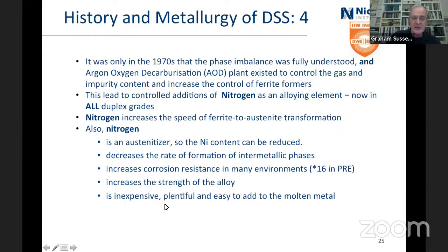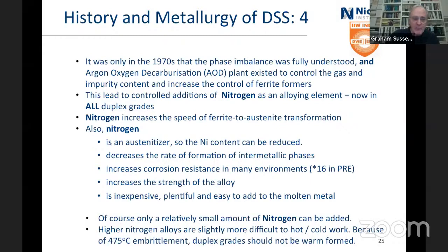It's nice and inexpensive, it's plentiful, it's easy to use. The only problem is you can't go beyond about 0.6%, but still, that's good and helpful. Of course, only a very small amount is needed, as I've said, just 0.6. The higher nitrogen alloys are a bit more difficult to hot work, and because of the 475 embrittlement, you shouldn't really go warm forming. Well, okay, up to 300, maybe you could.